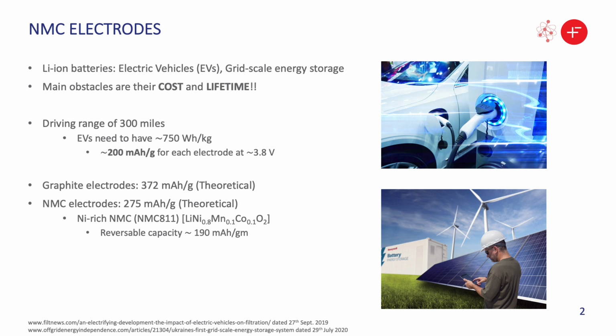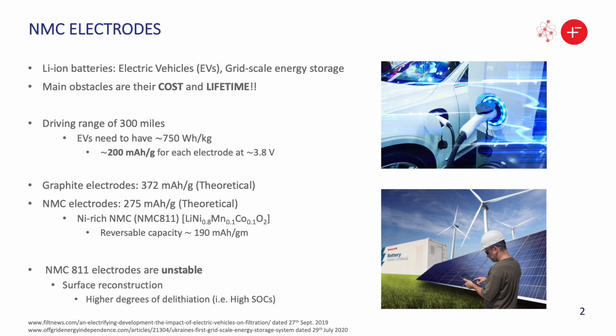Now, why is that so? What are the reasons why all the lithium cannot be extracted from the NMCs? One of the reasons is that NMC electrodes are unstable at higher SOCs. Basically, at higher degrees of delithiation, NMC electrodes go through a structural reconstruction.